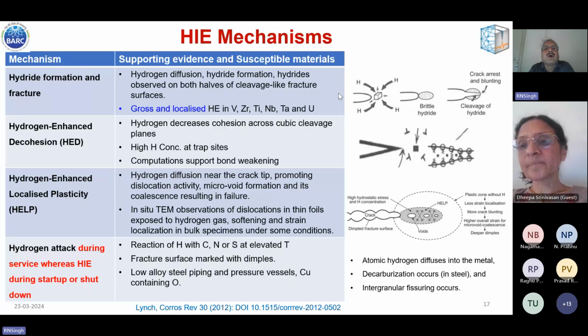However, in some titanium alloys, especially if you treat them in a vacuum, the hydrogen will come out, and there it becomes an issue. Similarly, for iron and steel, hydrogen can diffuse into the metal, and it can diffuse out also very quickly. So one has to be cautious, especially with pre-charging. People electrolytically pre-charge the steel sample with hydrogen, and if there is a long delay between charging and testing, the effect of hydrogen will not be captured.